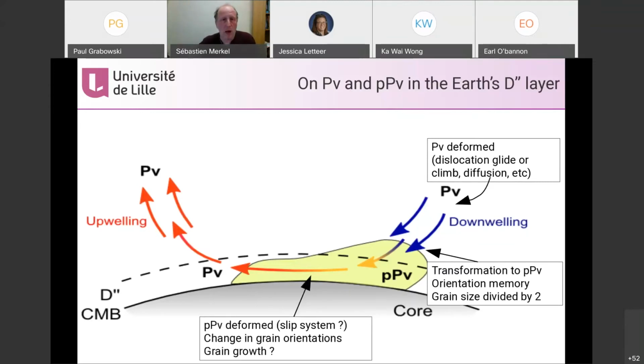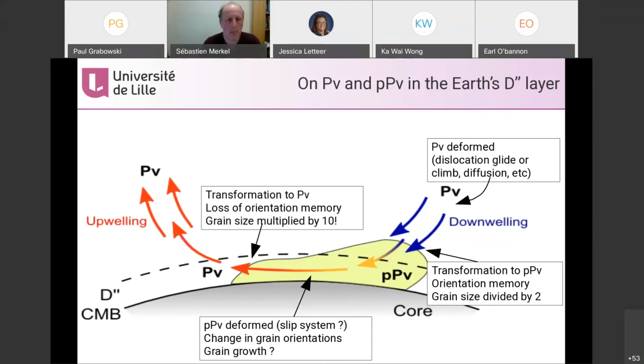Then, as your material is going down along the core mantle boundary, you will have changes in grain orientation through plastic deformation, through motion of dislocations or whatever, maybe grain growth, and develop a new type of anisotropy, a new type of texture, new type of microstructures. Then, when you'll be reaching a region of high temperature where you transform back to perovskite, you will lose the memory of all of that, and you'll have clean material.